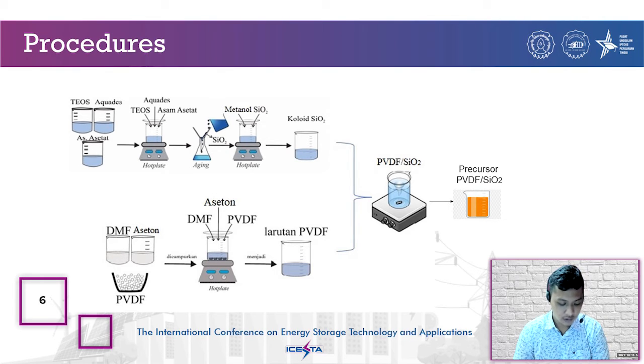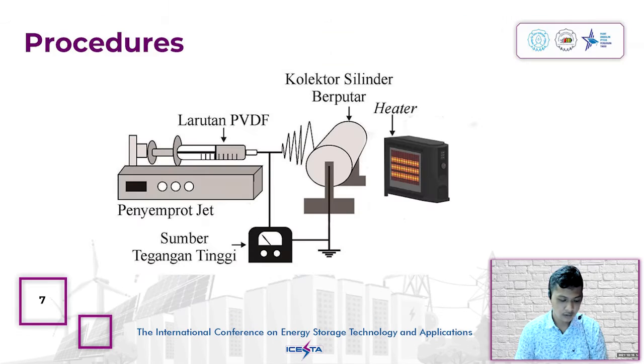The PVDF SiO2 precursor was prepared by mixing DMF and acetone in a certain volume ratio. Then PVDF was added at 50% of the total mass of DMF and acetone. Lastly, colloidal SiO2 was added according to predetermined variation, and the mixture was stirred for 8 hours at a temperature of 60 degrees using a magnetic stirrer.